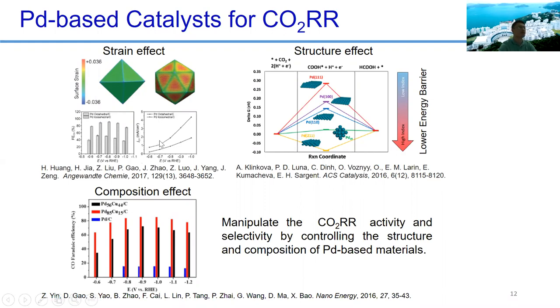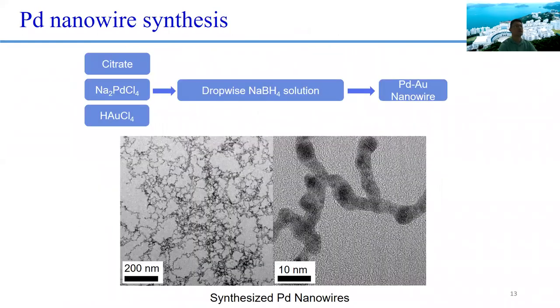Okay, so typically you generate a higher product efficiency for the carbon monoxide production. And if you're using different facets, for example, 111, 100, or 110, you can see that the reaction rate and the product efficiency are also different. Or you can make an alloy, so the surface is actually alloyed with different foreign elements. So you can see that it also has a big impact on the product efficiency, typically for the carbon monoxide. So our idea is that we're using nanowires, okay, to generate a lot of grain boundaries. So that means the defects. And once you have defects, then the adsorption energy of the reactants and also reaction intermediates will be different.